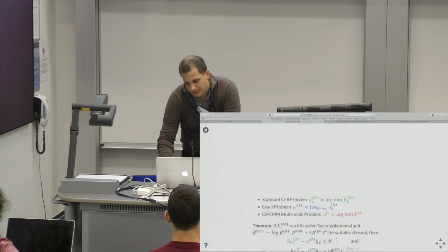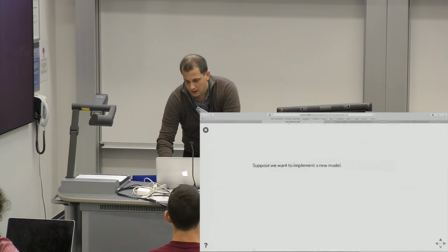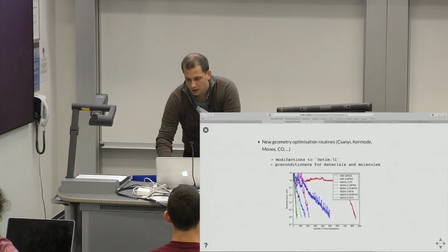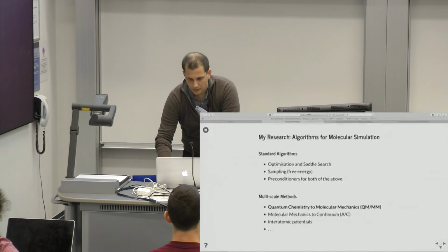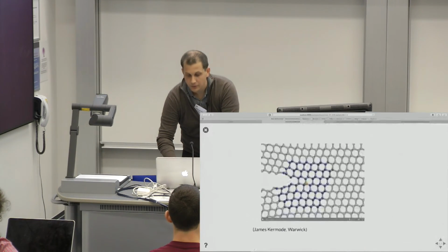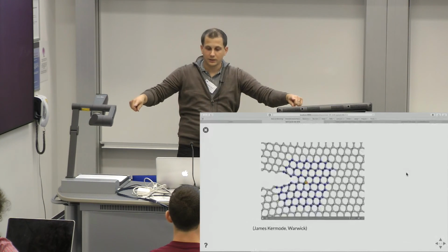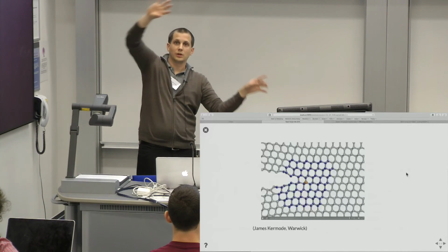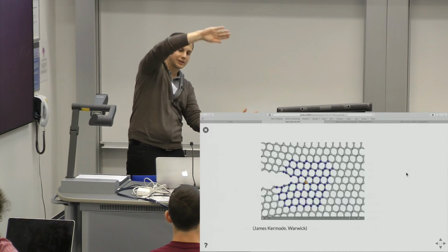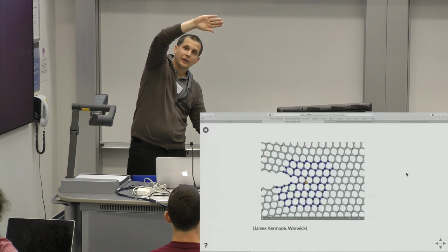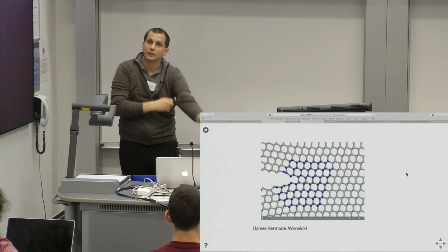Let me go concretely to the crack so you know what one does here. This one, right? What happens here is much bigger. You clamp atoms at the top and bottom edges, and you pull the crystal slightly apart to open the crack, and that creates a stress field that acts on the crack tip and drives everything forward.